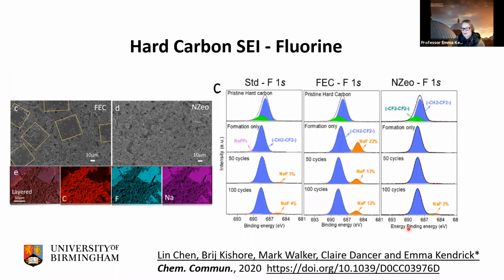Essentially, we saw that by adding in the nanozeolite, we definitely had a greater stability of the interface layers, in that the peaks didn't change that much over time compared to what you saw without the FEC. But you can see here we're starting to get some sodium fluoride formation again. So it does look like we've kind of mopped up bits and pieces, but it does have a finite lifetime. So the trick is to not get water in it in the first place, and that's actually quite difficult to do.